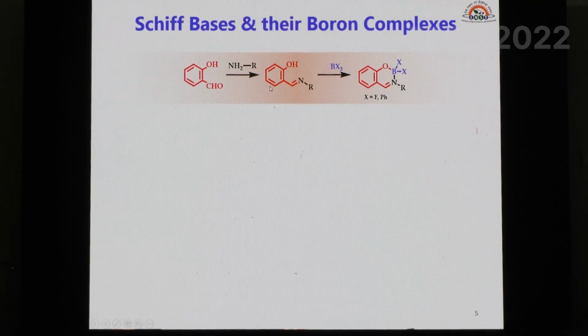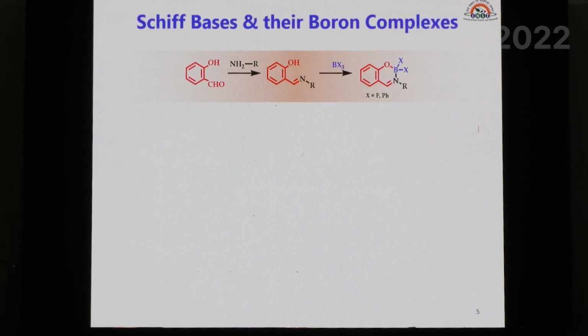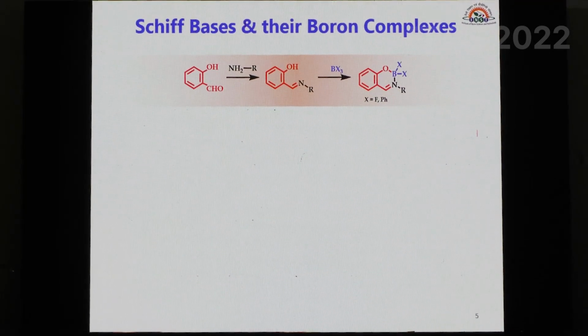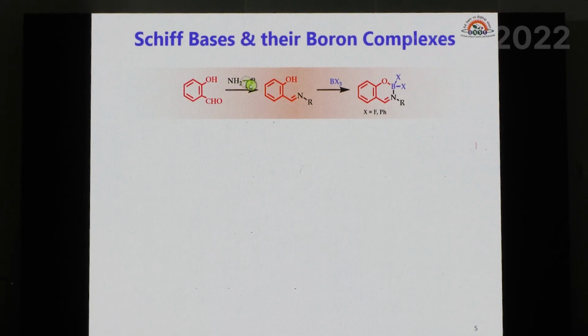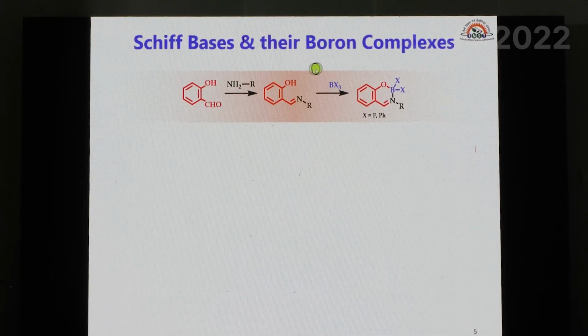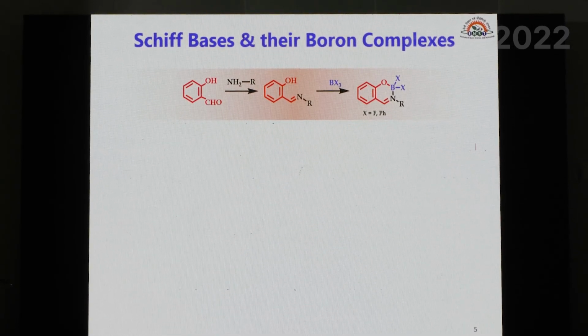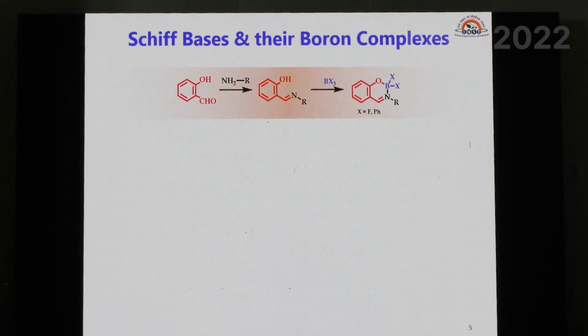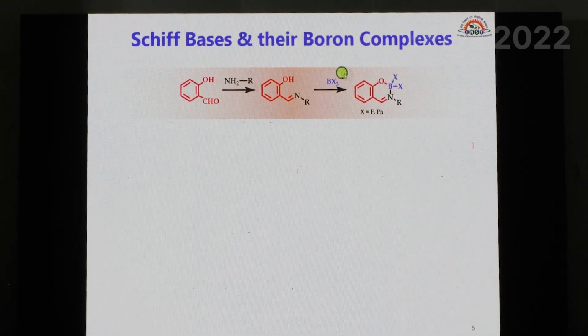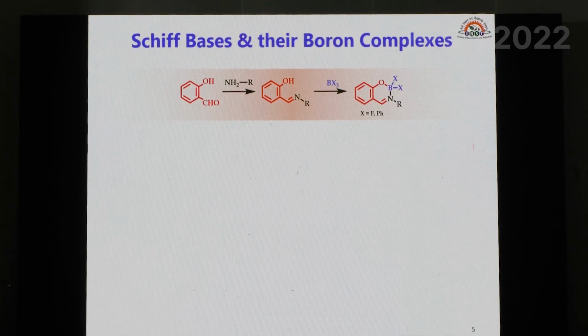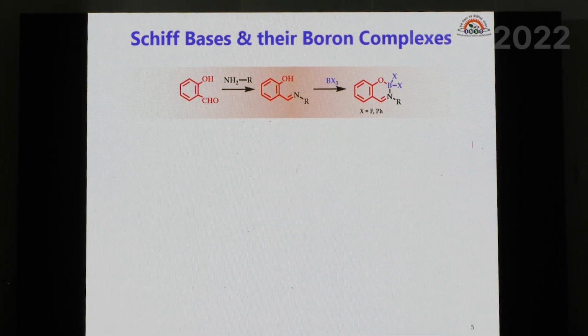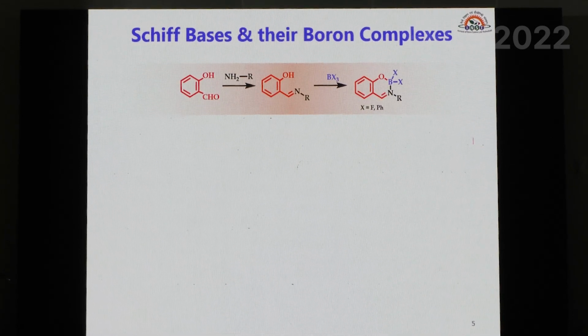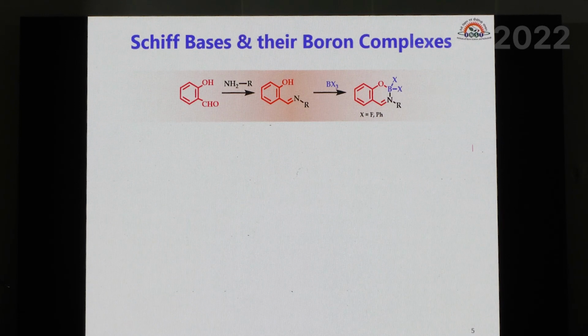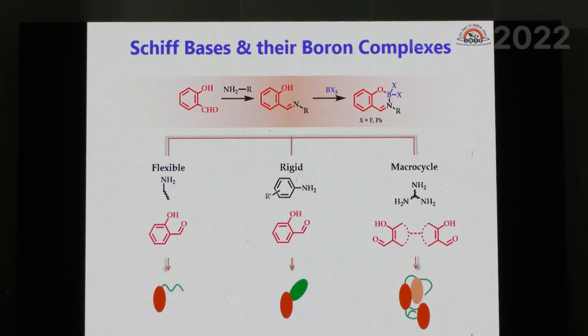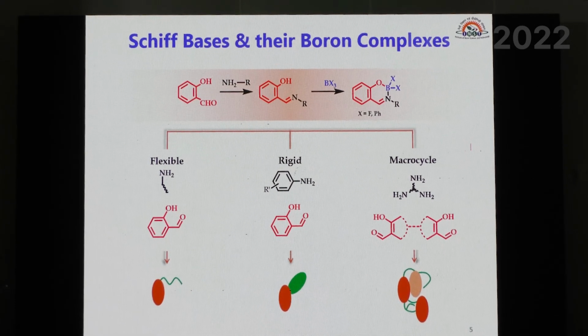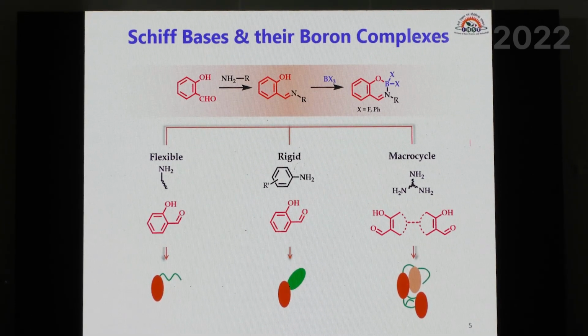This is one of the very simple reactions that anybody can see. It's a reaction between a simple aldehyde group and an amine giving an imine compound or a Schiff base. And we use salicylaldehyde based compounds because we have this additional hydroxy group, which can further aid in stimuli responsive properties. That means it can respond to an external input. And we are also interested in further complexing this compound with boron. Boron is an electron deficient element. And when it complexes with this Schiff base, it forms a 5-membered or 6-membered ring, in this case a 6-membered ring. And that leads to further changes in its electronic levels, which eventually transforms into better optical properties.